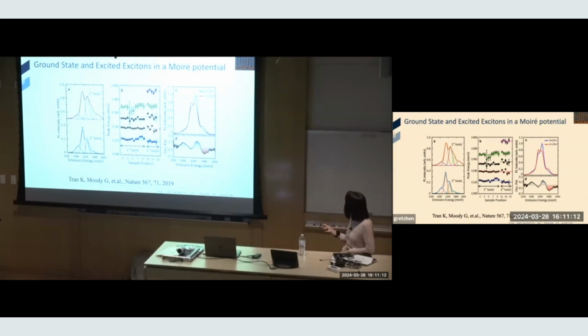And then the next thing is we got lucky with this sample that in photoluminescence, we're able to see exciton with alternating preferred polarization, circular polarization. Remember, I told you there's a spatial pattern of polarization changes. So maybe this is another hint. Perhaps they're related to these Moiré systems. We still cannot be sure.